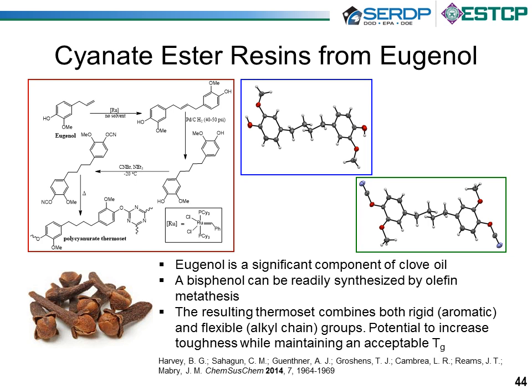Anyway, the reason eugenol is so interesting is it has a pendant alkene group that we can actually do a metathesis reaction on to form a bisphenol. We can do this reaction without any solvent, so it's run neat. And then simple hydrogenation gives us a saturated bisphenol. You can see the synthesis of it there on the left. It's a very symmetric molecule, so you can see both the bisphenol on top and a crystal structure of the cyanate ester on the bottom.